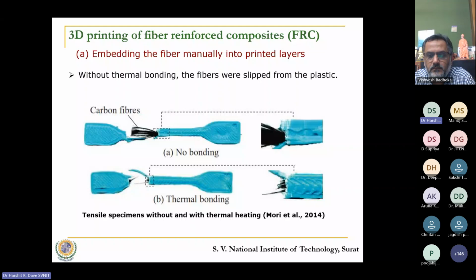So mixing of the carbon fiber into the polymer, even though manually, but with proper thermal heating, gives us a specific type of composite part which shows extended strength of the polymer part because of the bond that it creates with the carbon fiber. This is specific to carbon fiber. There are results available with glass fiber wherein a similar type of observation is reported.